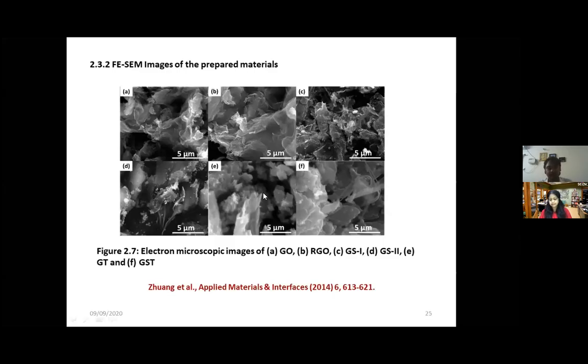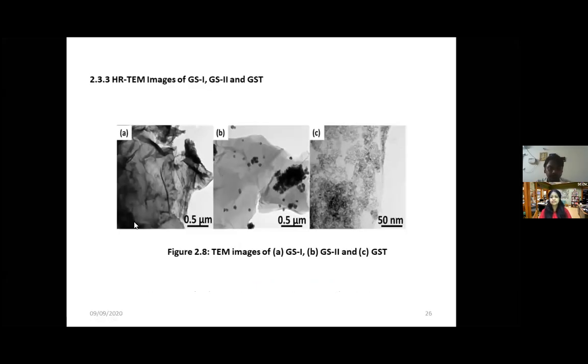Imagine what if the metal oxide is not present here. All the graphene oxide sheets tend to agglomerate, tend to restack due to the van der Waals force. If it restacks, there won't be enough surface to volume ratio for the gas to get adsorbed. Vice versa, if only nanoparticles are present and the graphene oxide is absent, what happens? All the nanoparticles tend to agglomerate and become a big particle size. In the next slide, I'll show you.